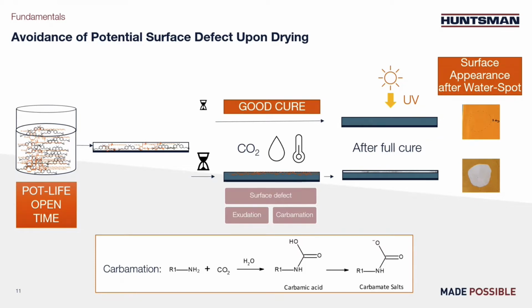When you are in the second case of a bad cure, the lower part, you see white traces which will remain for good. Different phenomena can be visible: white spots in case of water droplets, blushing of the wall surface in case of high humidity, or a sticky, greasy surface in case of exudation. Basically, many defaults are possible which can be amplified at low temperature due to longer cure or unexpected high humidity. Hence, the choice of hardener is critical.